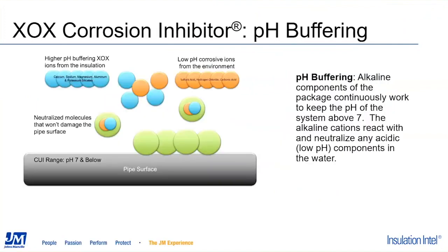So let's take a look at what the XOX corrosion inhibitor is doing and how it can help contribute to delaying or significantly protecting against the opportunity for corrosion to occur. The XOX corrosion inhibitor is basically an alkaline compound. It's a combination of calcium, sodium, magnesium, aluminum, and potassium silicates. These alkaline components introduce a high pH or alkaline nature to the insulation system.